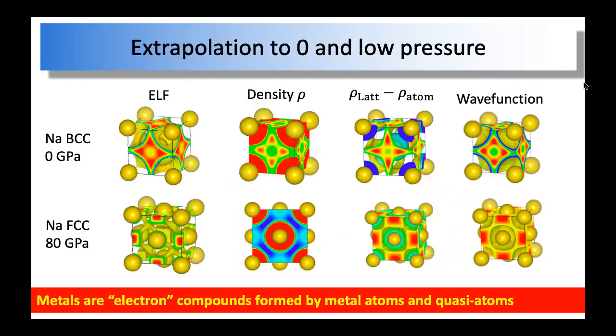Okay, so how do we apply this to metal structures at low pressure, or at ambient condition, just 0 GPa or one atmosphere, right? For DFT calculation, one atmosphere is 0 GPa for us. Well, not true, but we usually don't see that small difference. Anyhow, let's say for sodium, the 0 GPa structure is body-centered cubic, right? And for sodium at 80 GPa, the most stable structure is the face-centered cubic, the FCC structure. If you calculate the ELF, you can see an ELF pattern like this for BCC at 0 GPa, and an ELF pattern like this for FCC at 80 GPa.